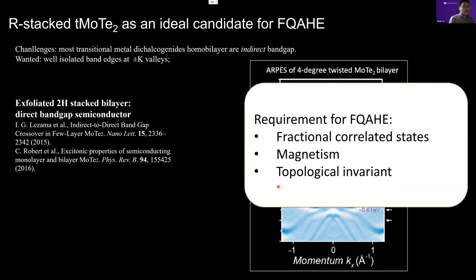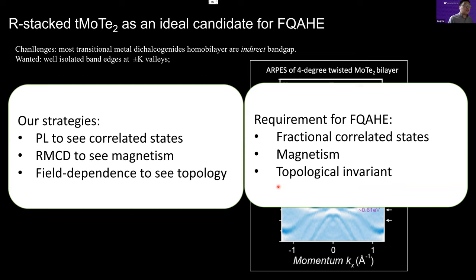We can have a checklist. What are the requirements for a fractional quantum anomalous Hall effect? It's fractional correlated states, magnetism, and topological invariant. And then we can do a one-to-one check with our optical methods. For fractional correlated states, we can use photoluminescence to see them. For magnetism, we can use magnetic circular dichroism to see them. And for topological invariant, we can use field dependence to adopt the previously introduced Streda formula to see the topology.